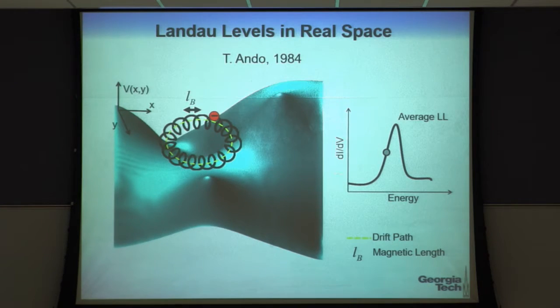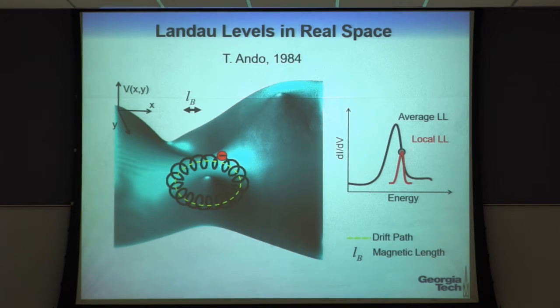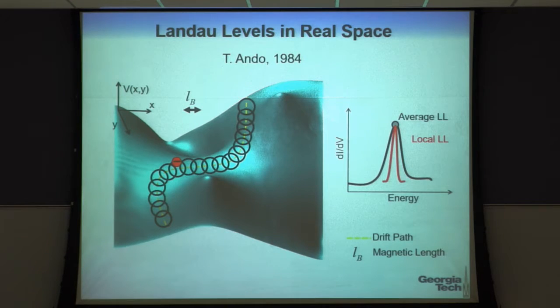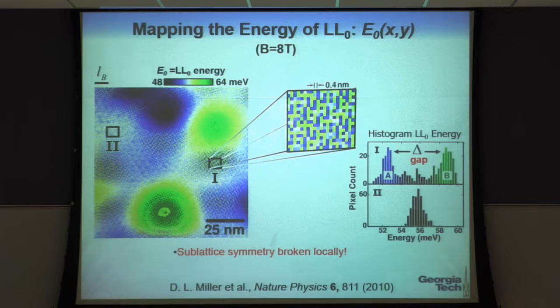And if I look at the average Landau level, that's energies over here. But if I take the STM looks locally, and it sees only a Landau level that has a shifted energy because the potential of the surface is a little bit different. So this gives us a way to actually measure potentials on the surface. And if I look around a bump in the surface potential, I see the energy of the local Landau level up here. And again, at the average energy, I get this thing running along lines, which connects one side of the sample to the other.